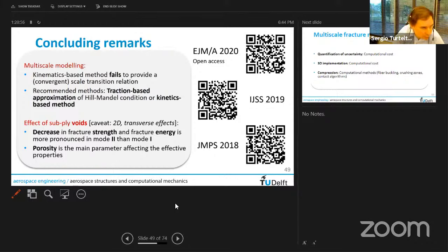And so, with your first question, which is about the properties of the RVE: a priori, you don't know how big your domain has to be in order to be an RVE. That's why you need to do this convergence analysis, in the sense that you take one domain and then you start to make it bigger and bigger. And every time you have a bigger domain, you compute the effective properties. And you check that at some point they don't change anymore. So it is part of the output.